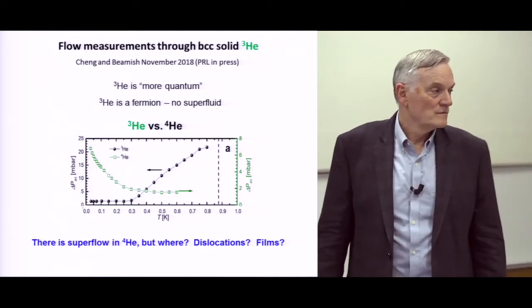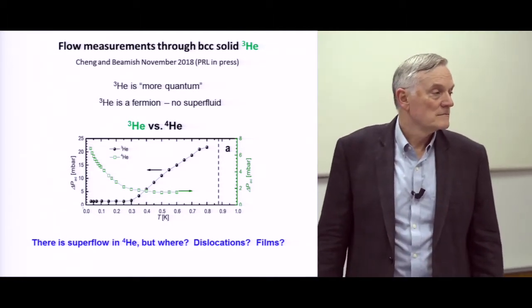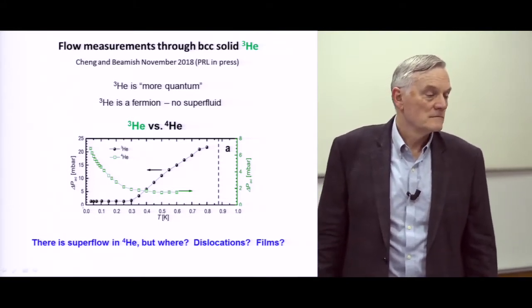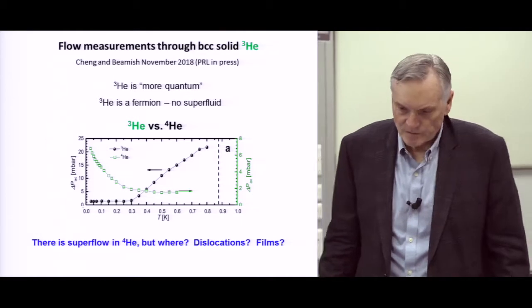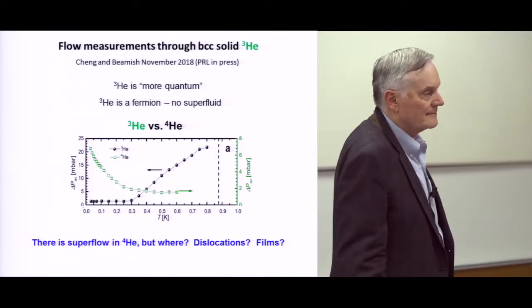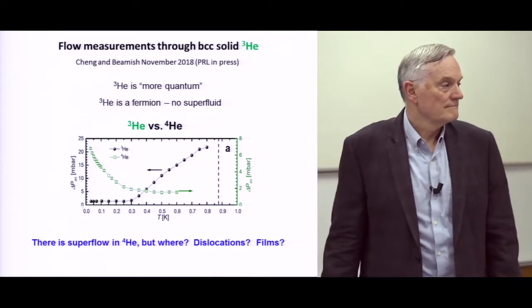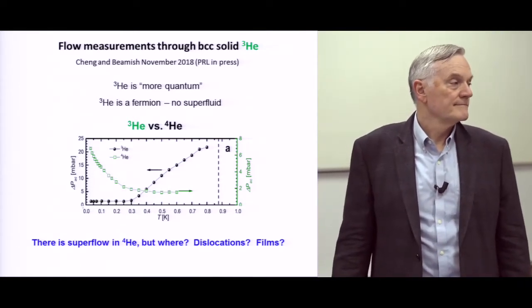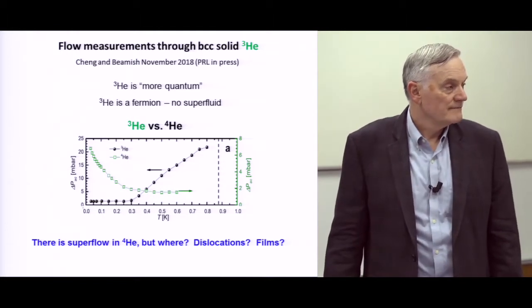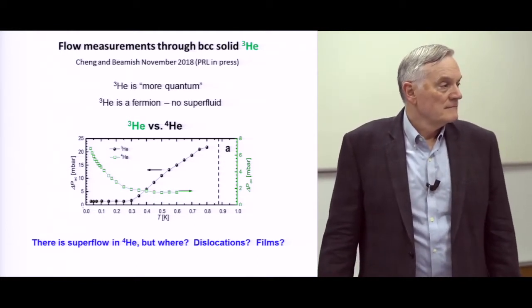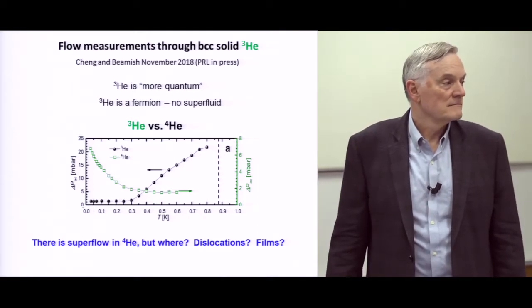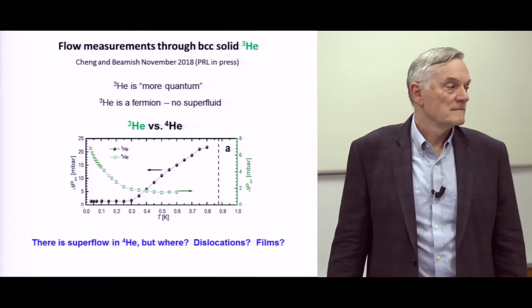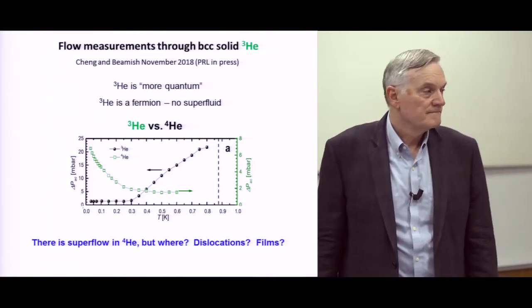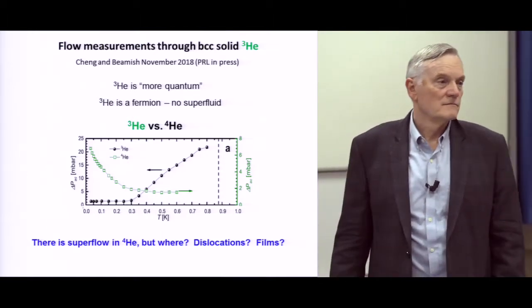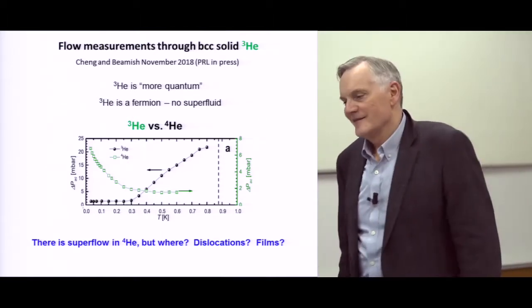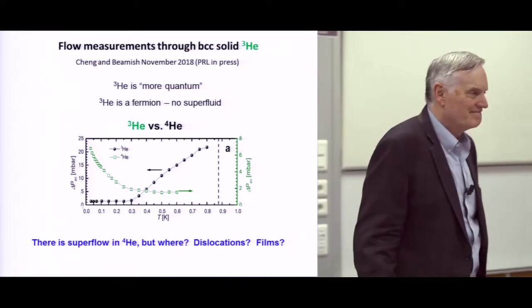But then there is another possibility, because these experiments are made with polycrystals, which is that any grain boundary, when touching the wall, makes again a liquid channel, because for reasons of surface tension balance, the boundary arrives here and then opens into a sort of liquid region, which has a triangular cross section. You see exactly what I mean. And we see that actually, it's observed. So where are we exactly in the discussion of the right place where this flow takes place?